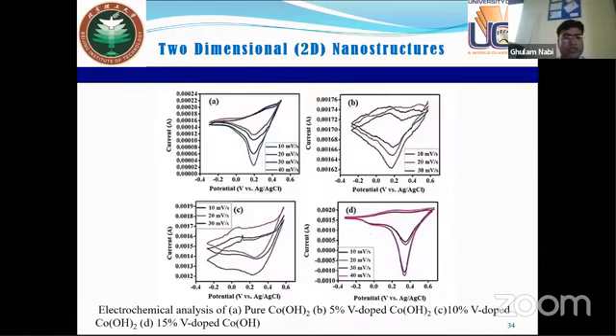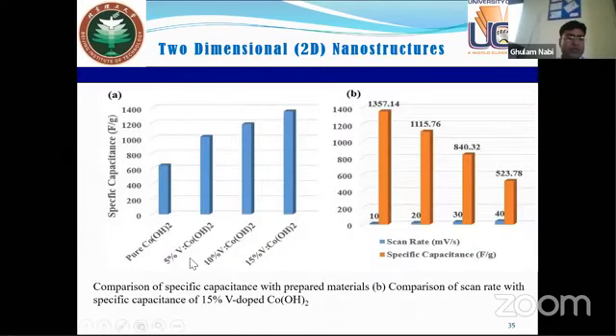So here is an electrochemical analysis of these materials. In A, we have used the pure one, and in B, C, and D, we have used 5%, 10%, and 15% vanadium doped cobalt hydroxide. So we can see here that if we increase the concentration of the vanadium, then the specific capacitance of the cobalt hydroxide can be increased. Similarly, as we increase the scan rate, the specific capacitance decreases.